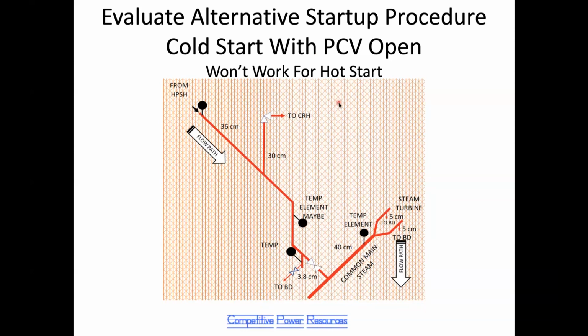So I'm not suggesting this will always work in every case, and it may or may not work in your plant. But if you are having erosion problems with the bypass, you may be able to improve things somewhat by sneaking up on whether you can make a cold start with the bypass open and do less damage. You cannot do this on a hot start. If you've got pressure in the boiler, you cannot open this bypass to a large opening just because you want it to be open. You'll overpressurize your reheater and cause all kinds of other problems. So this will only work for a cold start.